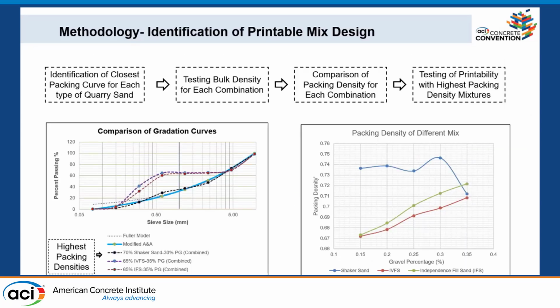From the previous model, we have found the highest packing densities for each type of Quarry aggregates, that is the Quarry sands and the pea gravel. We have found the 70% and 30% range for the shaker sand and pea gravel, 65% and 35% for the Indian village fill sand and the pea gravel, and also for the Independence fill sand and the pea gravel, we have found 65% and 35% for the highest packing. With the highest packing curve, we have calculated the packing density from the bulk density calculation, and here we have found that the numbers match with the optimization curves.